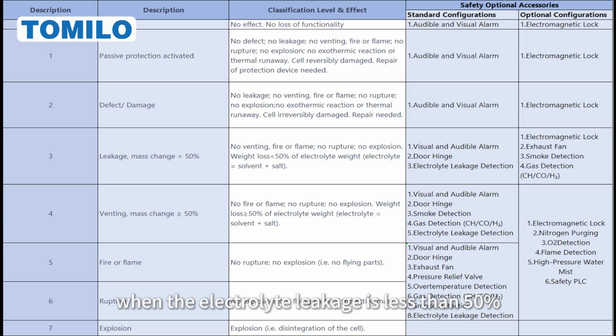That is, when the electrolyte leakage is less than 50%, it belongs to level 3 thermal runaway. When the electrolyte leakage exceeds 50%, it belongs to level 4, a dangerous level. When the battery undergoes thermal runaway and catches fire, it corresponds to level 5. When the battery ruptures and its casing breaks, it belongs to level 6. What is level 7? Level 7 means the battery directly explodes.